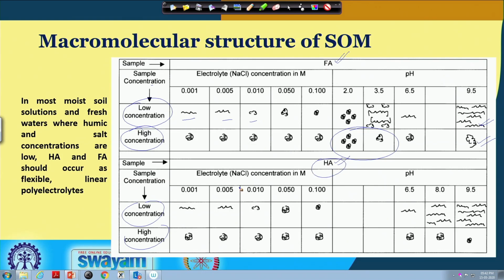Similarly, in case of humic acid also, at low electrolyte concentration and low concentration of sample, we are getting the fibrous like structure. However, at higher electrolyte concentration like sodium chloride, we are getting spherical structures, and in case of higher pH, just like in case of fulvic acid, in case of humic acid also we are getting fibrous structures, and in the combination of high concentration and low electrolyte concentration, we are getting spherical structures, and also in case of pH, at different pH conditions like 6.5, 7, 8 and 9.5, we are getting spherical and rigid structures. So, this is how, depending on the concentration of the sample as well as the electrolyte concentration and pH, the structure of different humic acid and fulvic acid molecules changes.